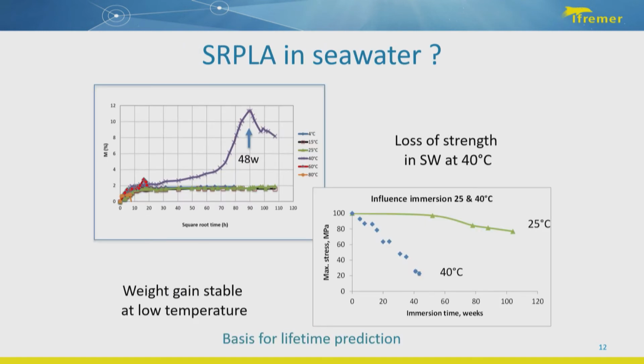So here you can see different graphs. On the first graph, on the top, you have the weight gain as a function of the square root of time. We have used this scale due to the diffusion law. What we have done is immersion at different temperatures in natural seawater, from 4 degrees C, which is the temperature in deep sea, up to 80 degrees C, and a lot of different temperatures in between, to perform accelerated aging tests.